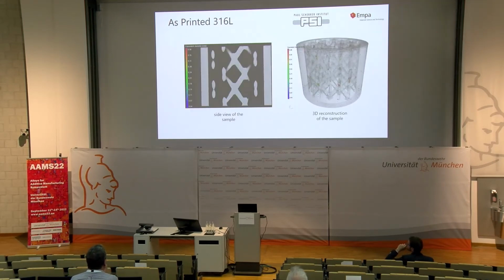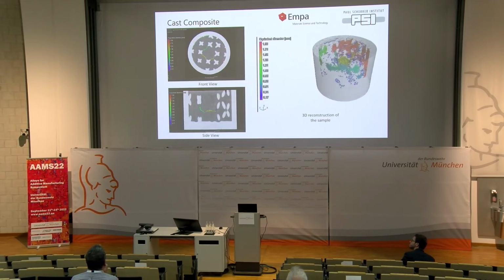cracking. For the as-printed structure, we notice that in general we don't have an intense presence of porosity, especially at the contour part, but we do have some smaller pores, around 0.20 millimeters, appearing at the edges of the internal structure. For the as-cast structures, we see the appearance of porosity at the interface between the contour and the casted part. Actually, this porosity is like a plane, so we can talk about a detachment between the copper part and the steel part, and we can attribute this, for example, to shrinkage of material during its solidification. Secondly, we can see also the appearance of cracking at the central part of the sample.